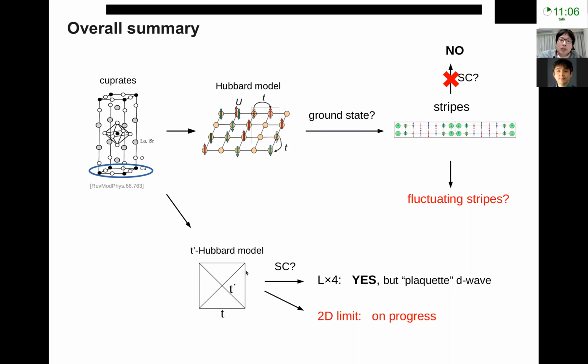And if we consider a cross hopping T-prime, then on this spatial geometry or finite size, we indeed get long range superconductivity, but it actually has plaquette D-wave rather than the ordinary D-wave we expect from 2D. So we need to consider the 2D limit - this means finite size effect is very important, and we need to do a careful finite size extrapolation or some sort of finite size analysis on this system. This is still an ongoing work.